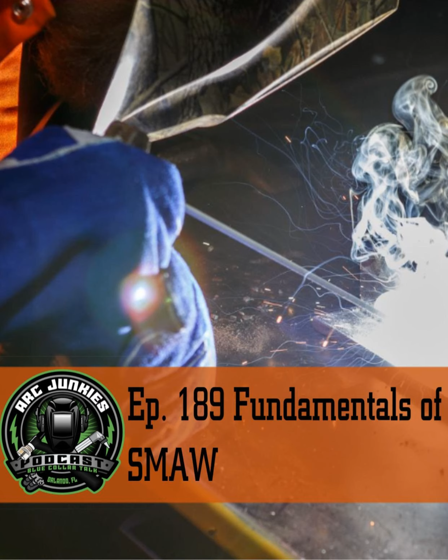Okay, if I get too far away, what's going to happen? Voltage is going to increase, amperage is going to decrease slightly. I'm going to start getting spatter in my weld pool. The weld's going to get much wider than I want. And especially if we get out of position and we don't have a tight enough arc length, I'm just going to start dropping metal everywhere. There's going to be little droplets coming off the rod. If you have little droplets coming off and falling into the puddle, you're too far out.